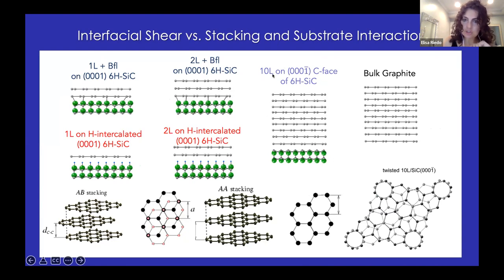Then we have a different system, which is a 10 layer graphene, but now grown on the carbon face of 6H silicon carbide. Because of this, the stacking is very interesting, with essentially twisted layers, where the layers alternate 30 degrees and 2 degrees compared to the silicon carbide axis. And then we work on bulk graphite. We performed interfacial shear modulus experiments on each of these samples. Always keep in mind that we shear a tiny bit the top layer compared to what you have underneath, the same here, the same here, and so on.